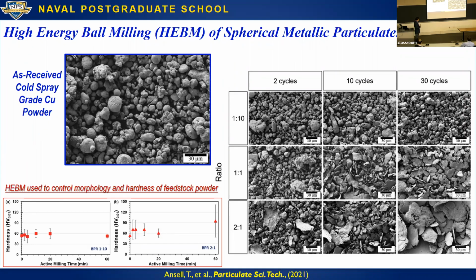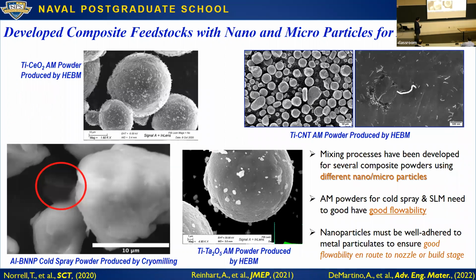This short study basically gave us a blueprint of what we could do with the high energy ball milling technique, but doing the inverse of that, using relatively low milling, where we're only going up to maybe 30 cycles, where one cycle is 2 minutes of actual milling and 5 minutes off. This gave us a blueprint of what we can get away with milling without changing the morphology of the particulates that much. If we go to very high energy ball milling conditions, we just get platelets, and this would never flow. So these are some of the composite feedstock powders that we've made.